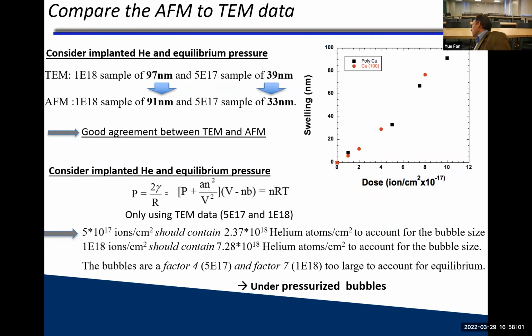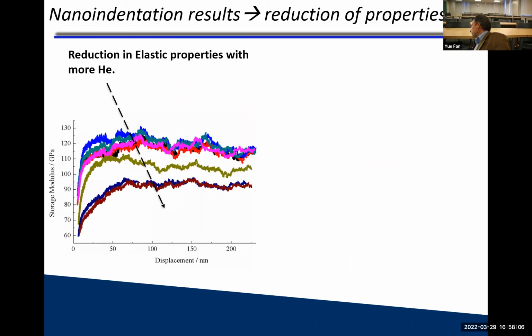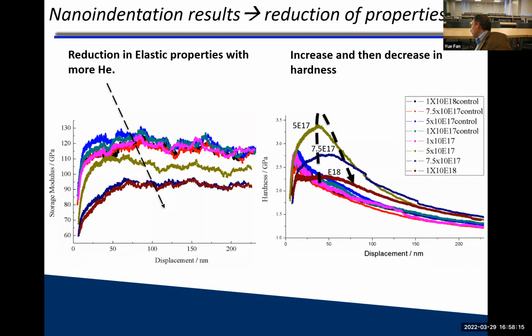So that was kind of interesting to do. Now the nanoindentation is also interesting. So we do indentation, displacement versus elastic modulus, so depth versus modulus at different doses, and hardness versus depth as well. Now, as more dose we pump in there, so this is unirradiated or control, I guess, and this is 1 times 10 to the 18, what we see is the elastic property drastically reduces. Well, it's not hard to imagine because now you have all this empty space. It's more like foam almost with this many cavities. And so your elastic property is reduced.